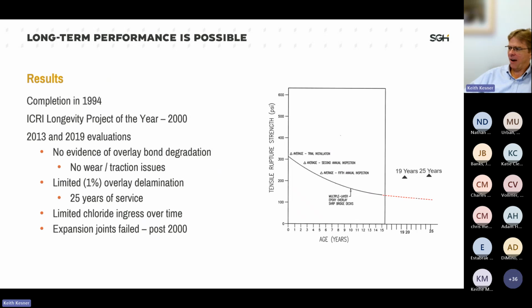We're still getting, as you can see in the graph on the right, good tensile rupture strength. Very little overlay delamination, no chloride ingress. One of the problems we had is our expansion joints failed basically as soon as the warranty ended. But what this is really telling us is that if we think about durability and repairs, we can actually get there.